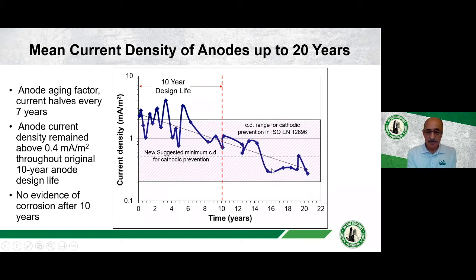Now, there's a couple of things that I could say about that. One is that the team that suggested this 0.2 to 2 milliamps, Pedeferri's team in Italy, later explained that in fact the newer results were showing that you probably need 0.4 milliamps per meter squared as your minimum. But also, when we're measuring the current density, we're taking a mean current density over the whole surface area, and between the anodes, it's likely to be probably half of what you're assuming to be the average. So even though we may be measuring 0.4, it probably is 0.2.